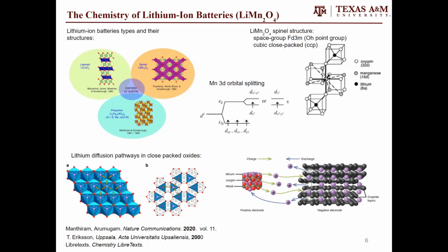When in a battery, lithium atoms will be sent to the spinel from the anode. When these lithium ions are inserted into the spinel, they intercalate and occupy the 16c sites. When this occurs, the lithium ions already in the 8a tetrahedral site are displaced into the nearby vacant 16c site, inducing a first-order phase transition.